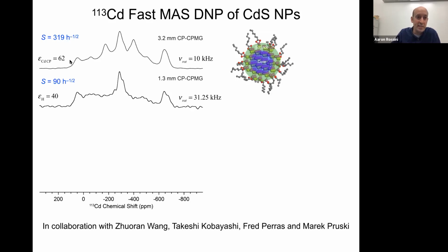So if we compare the absolute sensitivity, so that's going to be the signal to noise ratio of the cadmium spectra per the square root of the unit time, we see about a 4-fold loss in the cadmium sensitivity for these cadmium detected CPMG experiments. That's entirely expected because your 1.3 millimeter rotor has a much smaller sample volume than a 3.2 millimeter rotor. But it's only a factor 4 loss in sensitivity. And the nice thing about the faster magic angle spinning here for cadmium is because it has a very large chemical shift anisotropy, the faster MAS frequency can eliminate the sidebands and give you that isotropic spectrum, which you needed to perform an MAT experiment at the slower MAS frequency to get. So this actually does save you some time if you're interested in getting the isotropic spectrum.